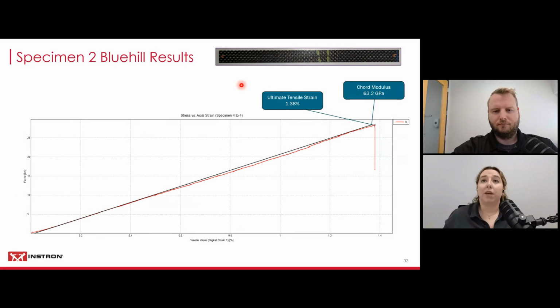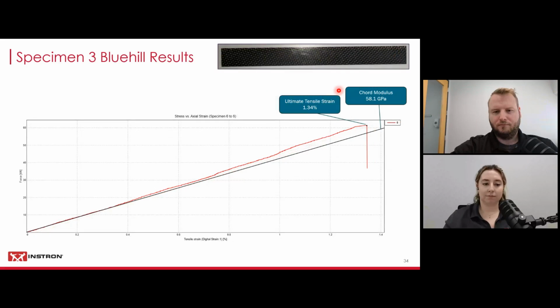Next, we have that untabbed specimen. Again, looks good, nice rise over run, a little more wiggly, but absolutely okay. We're still capturing our ultimate tensile strain at 1.38% and that chord modulus at 63.2 gigapascals. And then lastly, we have our largest specimen with the ultimate tensile strain of 1.34% and that chord modulus of 58.1 gigapascals.